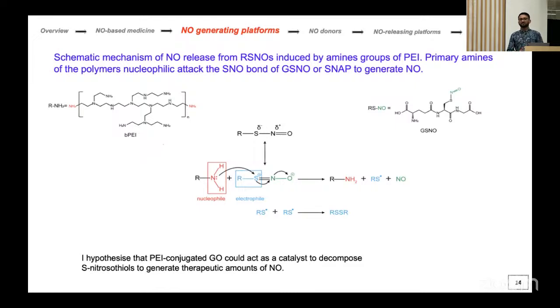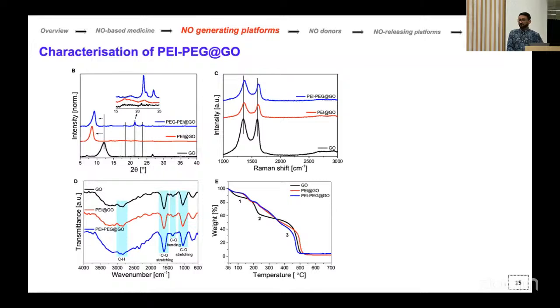So why not use polyethyleneimine on its own? Because if we use free amine groups, the problem is that nitric oxide production differs at the nitric oxide sources, as I mentioned, in the bloodstream, so they can make nitrosamines, and nitrosamines are carcinogenic. We don't want to produce nitrosamines in the coronary arteries. That's why we want a controlled system where the amine groups can interact with the nitric oxide substrate in a controlled manner. So that's the basic characterization.